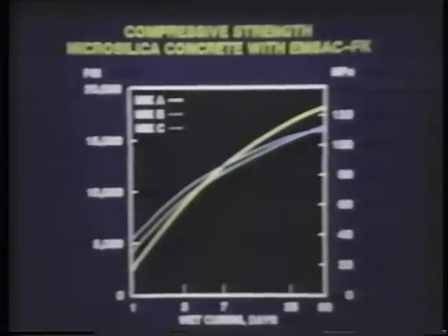At Neville Island, concrete containing EMSAC-FK additives tested over 10,000 pounds per square inch at 7 days and over 17,000 pounds per square inch at 90 days. In its specification for the Kinzua Dam Stilling Basin rehabilitation, the U.S. Army Corps of Engineers required the concrete to attain compressive strength of 10,000 psi at 7 days and 12,500 psi at 28 days. Slump was required to be from 7 to 10 inches. The contractor is Casey Company of Pittsburgh, Pennsylvania. The concrete was produced by Harmon Brothers Ready Mix Concrete Company in Warren, Pennsylvania.